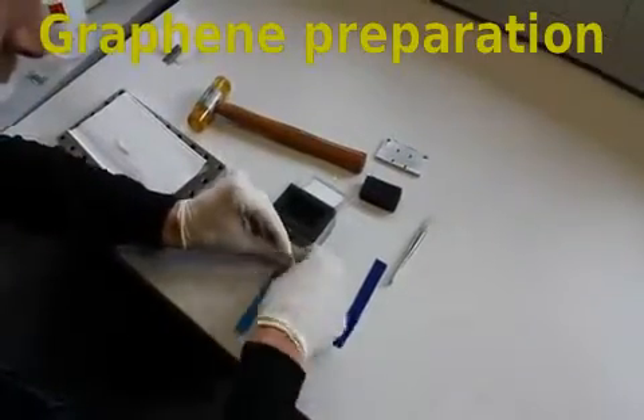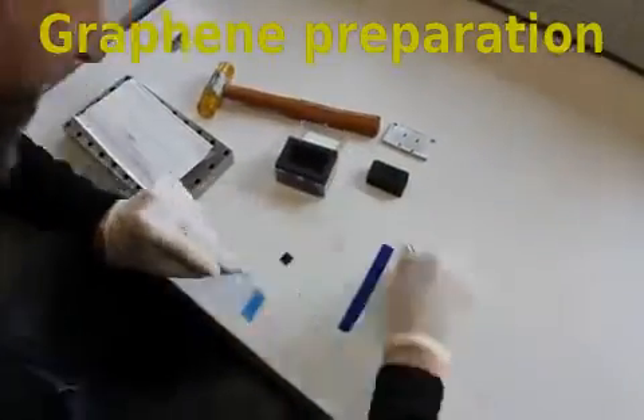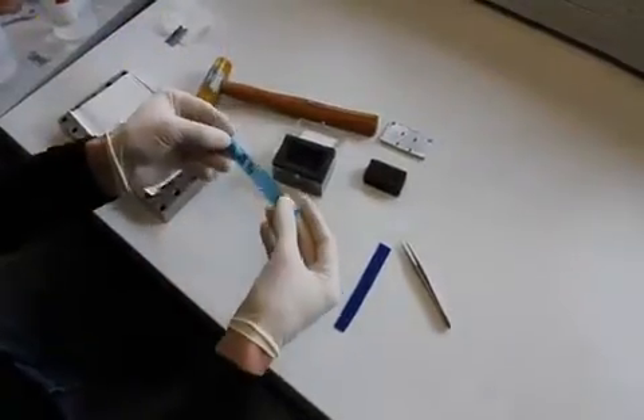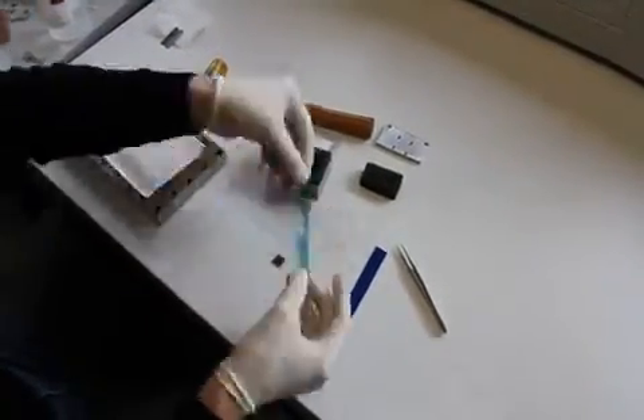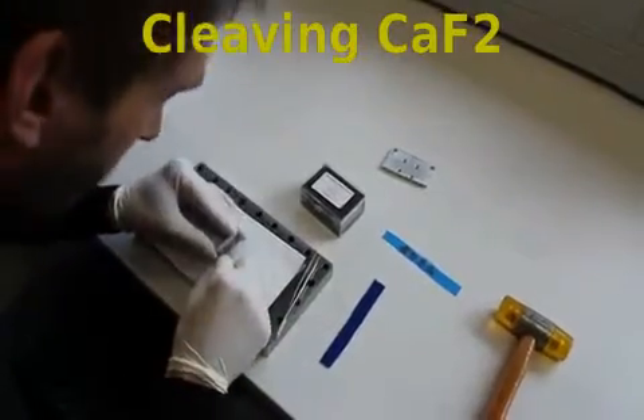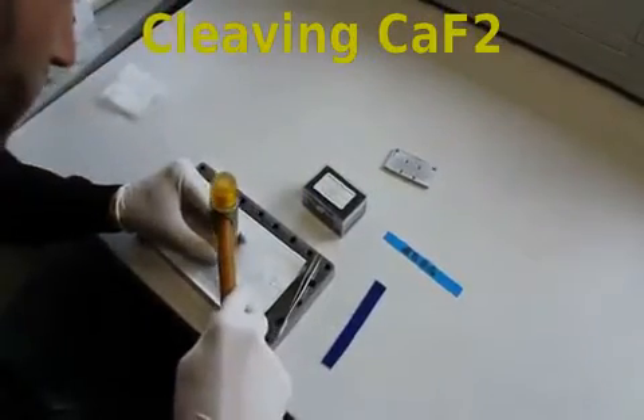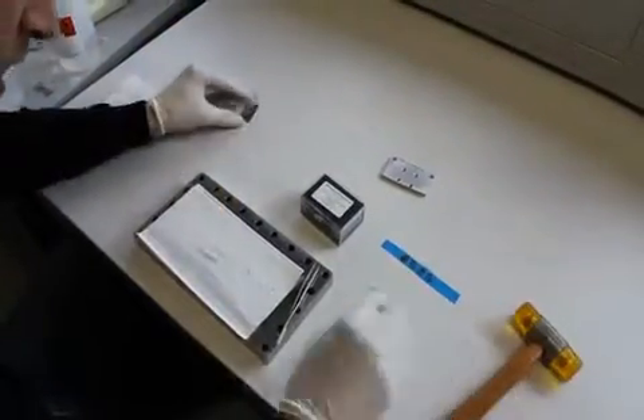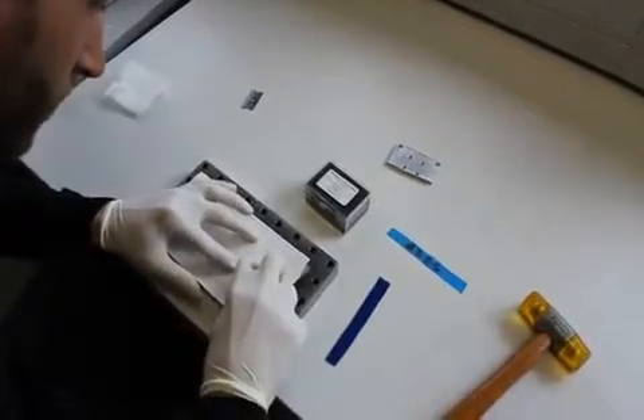In this research we identify and qualitatively describe the hydration layer which is confined between the mechanically exfoliated graphene and an insulating hydrophilic substrate, namely calcium fluoride. Graphene is exfoliated under ambient conditions, applying the well-known Scotch tape method. Calcium fluoride is cleaved under ambient conditions as well, resulting in a calcium fluoride 111 surface.